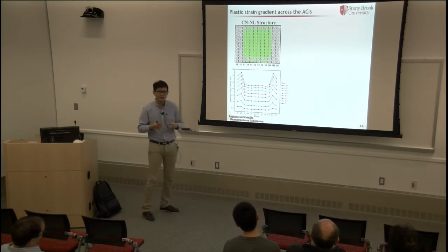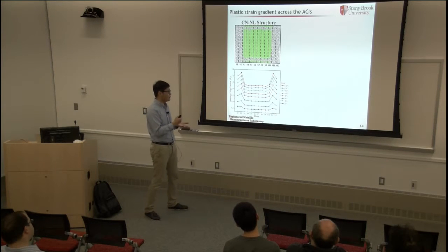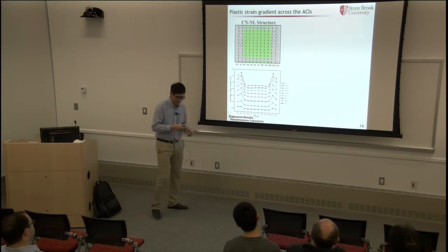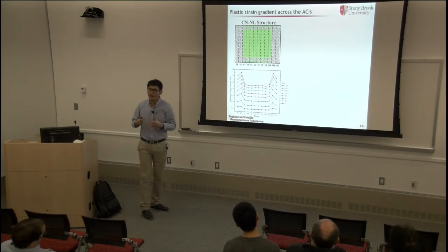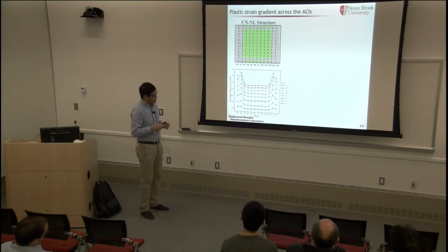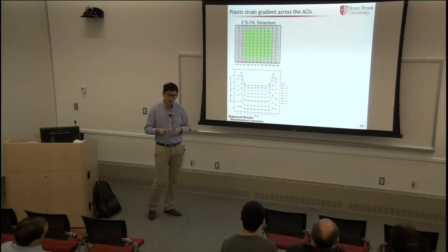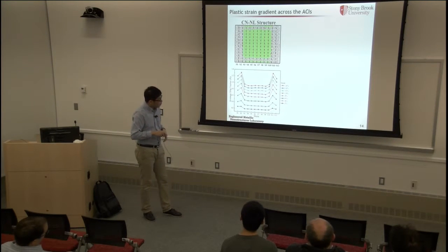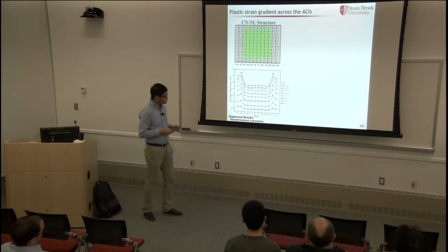And we combine different strains together to form this average slip vector map. It shows that before the dislocation emission, there's already a strain gradient across the intersection slices such as S2 and S3 and S10 and S11. With increasing strain, these strain gradients become more obvious, and even the crystalline interfacial slices become higher than the interior slices.